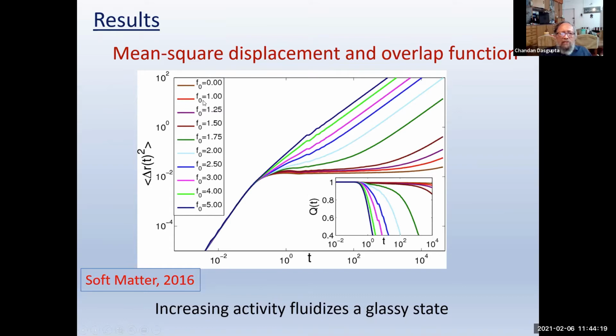But then you increase the activity, and these curves move in this direction. And then you can see that beyond a certain value of the activity, you begin to see this diffusive regime where the mean square displacement increases as a function of time in a linear fashion. So this is the fluidization. Increasing activity fluidizes the glassy state. It's similar to the experiment and also to some of these biological systems that we had mentioned earlier.